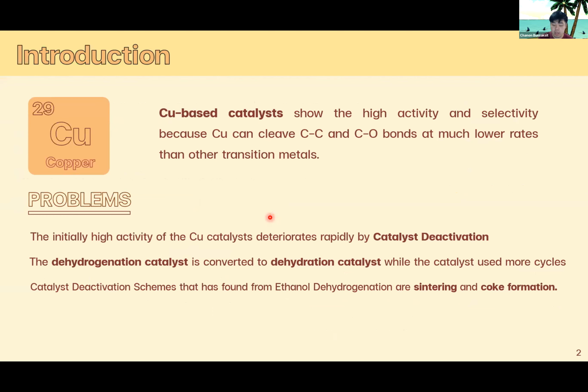Generally, the catalysts for alcohol dehydrogenation can be mainly divided into two types, including the metal and the metal oxide. Among these catalysts, the copper-based catalyst shows high efficiency and selectivity for the non-oxidative dehydrogenation of ethanol to acetaldehyde because the carbon-carbon bond is cleaved at a much lower rate than with the other transition metals. But unfortunately, the initial high activity of the copper catalyst deteriorates rapidly due to catalyst deactivation. And the problem found in the operating process is that the dehydrogenation catalyst is converted to a dehydration catalyst while the catalyst is used for more cycles. And the objective of this presentation is to show from previous articles how to improve the copper catalyst performance and reduce the catalyst deactivation problem.